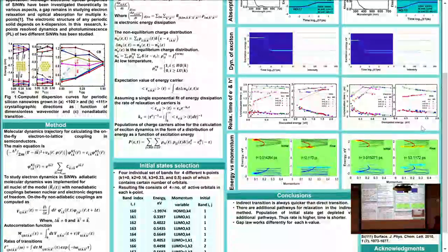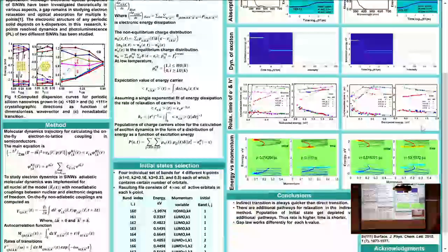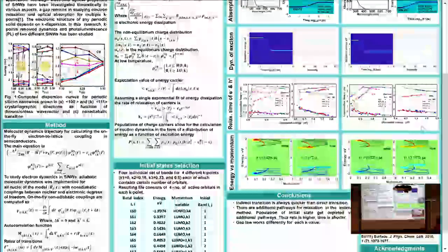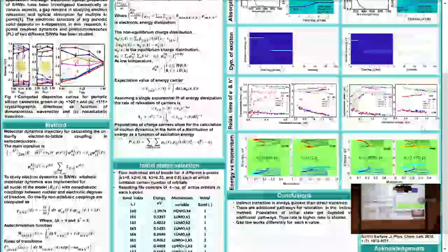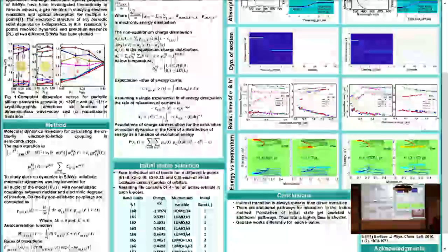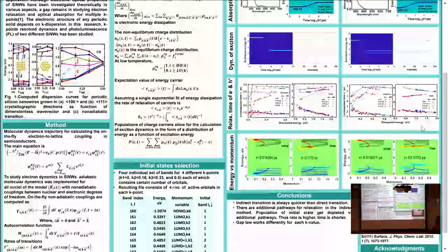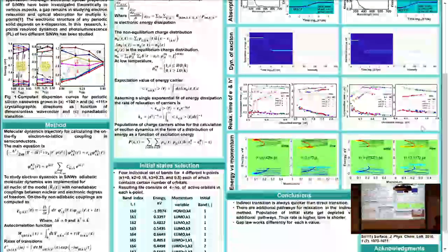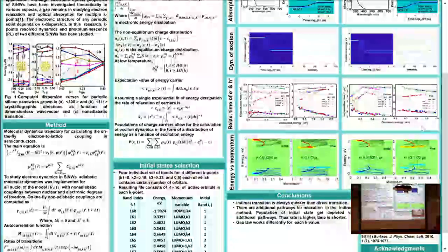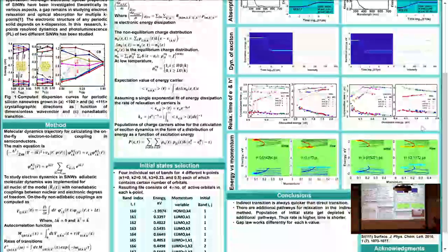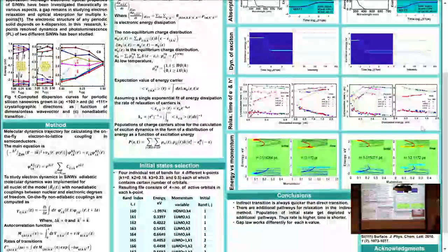Yeah, I understand. So here is the conclusion. We considered momentum restricted transitions and all transitions, which include momentum restricted and unrestricted. In the case of all transitions, relaxation is quicker compared to momentum restricted transitions, because there are additional channels for the charge carrier to relax to the band edge. That's all. Okay, thanks, ma'am.